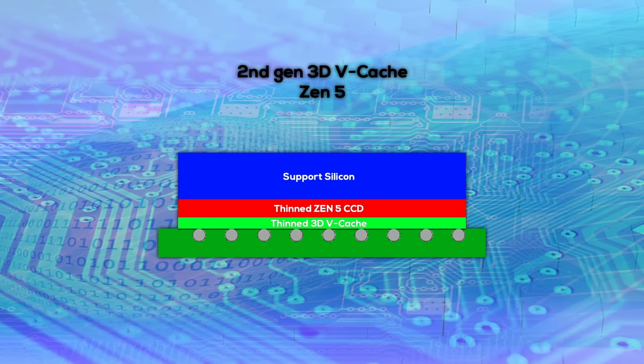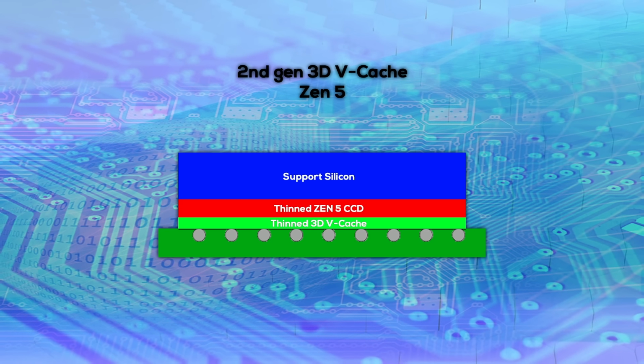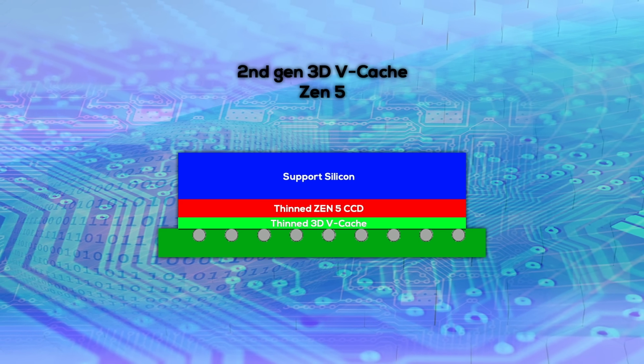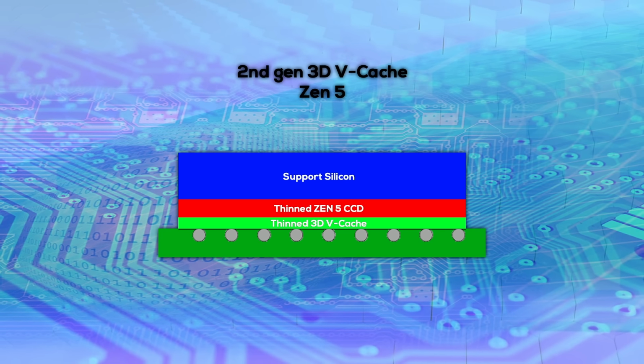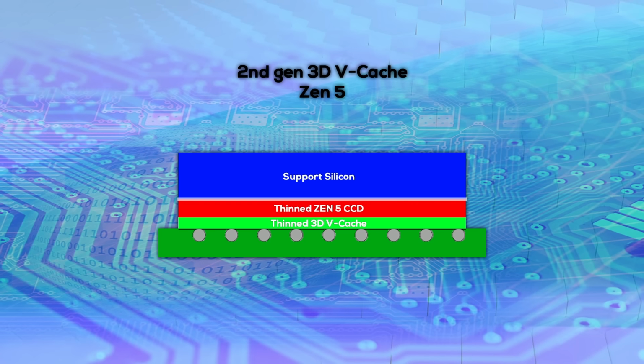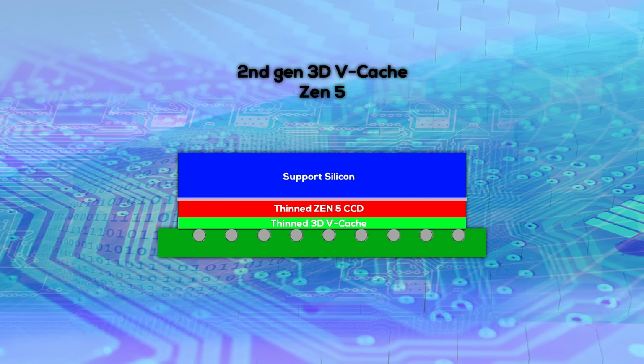The other possibility, and what I think is most likely, is that both cache and CPU chiplets are diced and binned before the bonding process. This would mean that AMD still works with two reconstituted wafers for the hybrid bonding process. And because TSMC currently only uses thin dies for reconstitution, it would mean that this approach still requires structural support silicon on top. The end result would look like this: super thin 3D V-cache die on bottom, a little thicker but still thin CCD above, and then a structural silicon on top of it. Of course, this would mean that there's still one oxide layer above the CCD, but that's half as much as before.